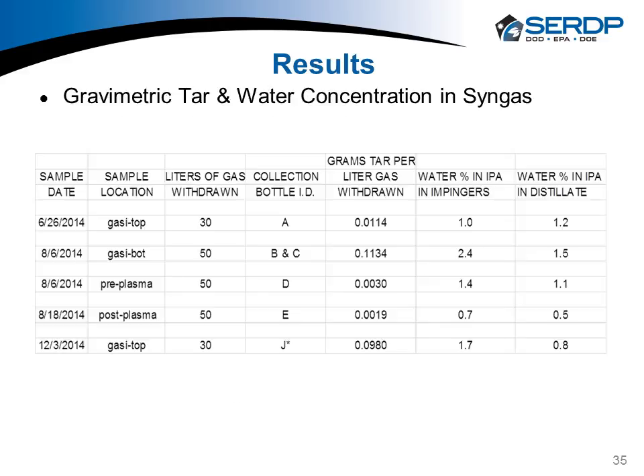For the gravimetric sampling, again, that's the heated tube drawing from the process gas through a flanged connection. The major thing here, I kind of discount this one. The gasifier top only had 0.01 grams per liter, whereas at the bottom we had 0.11 grams per liter. Pre-plasma and post-plasma, it decreased. Here, I'm not sure what was going on, the gas flow problem probably was. And then post-plasma, we see very little coming out, and we saw that in the GC mass spec that not much made it out of that plasma or the catalyst.